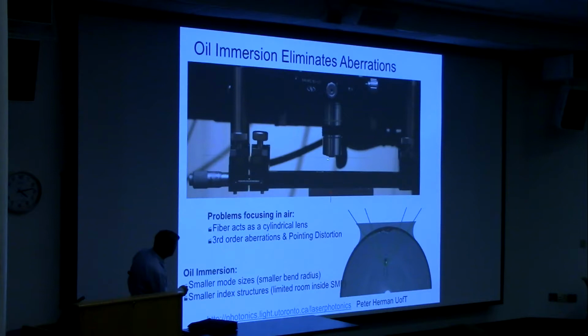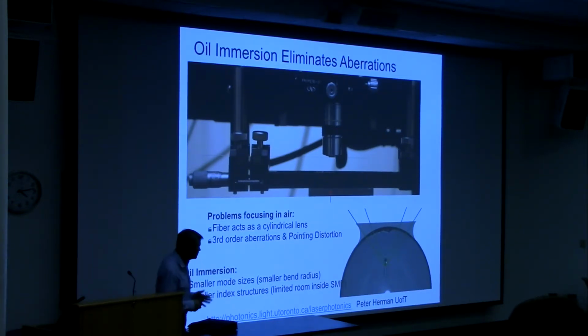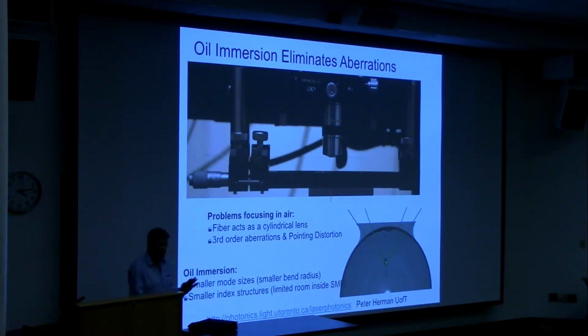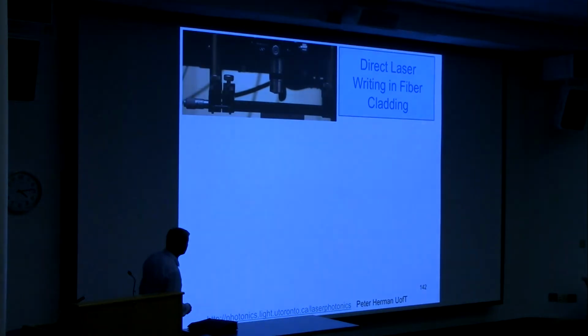We slide this bead of oil along a fiber. This is 4 inches of stripped fiber. They're clamped in place, and then we learned to get about 1 micron positioning resolution. So we can make structures relative to the pre-existing core waveguide to 1 micron. So with all of that, we could go back and ask, can we make waveguides that connect with the core? Can we open up structures, build microfluidics to do some kind of sensing applications? And in fact, it all does work.